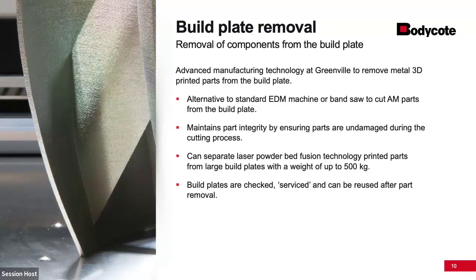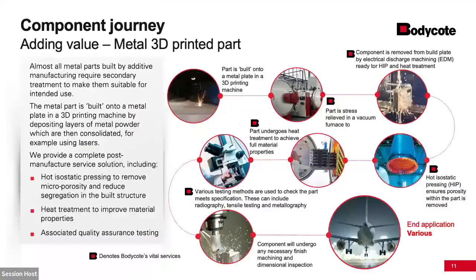So, component journey. Here's a typical part. You've got your 3D printed part. After that, the plate you've got to build up will come over for a stress relieve, typically in vacuum. After that, the part will be EDM'd. It travels over to a HIP for densification, back to a vacuum furnace to get your mechanical properties, off to a test house. After testing, maybe a final machine, and onto an engine blade somewhere on an aircraft, or from a medical standpoint, same thing: your hip, your elbows, and whatnot.